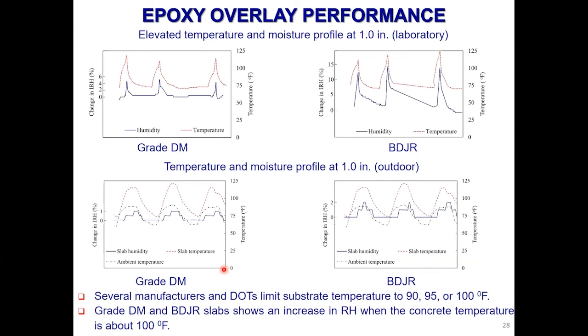So when we look at possible reasons, one we can see in grade DM mix with slag and type 1 cement: there's a significant increase in moisture when the temperature is more than about 90-95 degrees Fahrenheit. So there's significant moisture that is attracted towards the surface. In this one, it's lower; the increase in moisture is lower. So that's why we can see a performance reduction in grade DM or the mix with type 1 under elevated temperature.